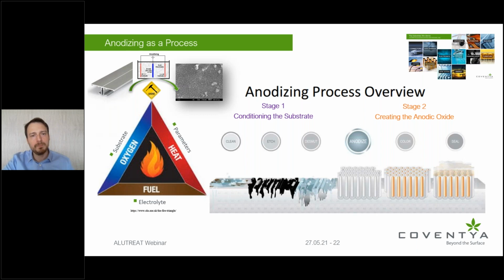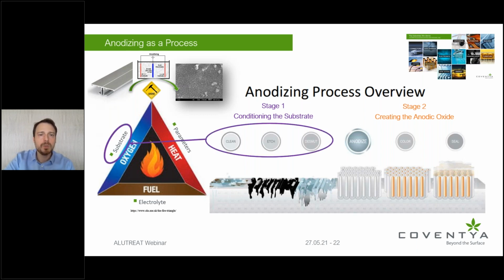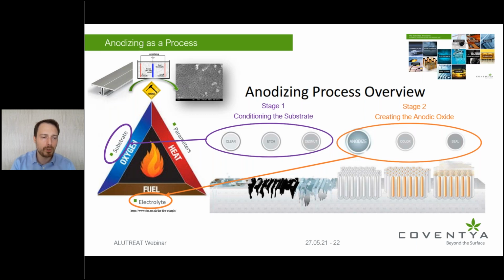Therefore, we are taking this approach from the plating side, that whatever you have or do not have on your substrate, it will be possible to condition by adjusting your substrate in a chemical manner. So we do not just single out the processes like anodizing or coloring, but, like we have shown with the fishbone diagram, we like to use the entirety of the process in order to give us more room to apply the parameters that are needed to structure the oxide layer, and also adjust the substrate so that we have a much more suitable base to grow these oxides.